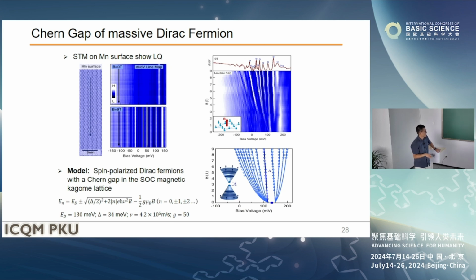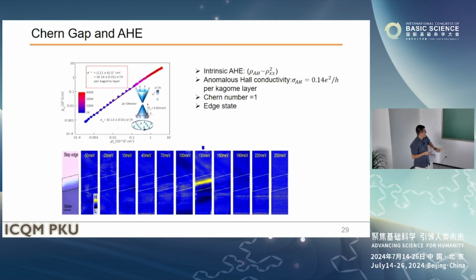Okay, so how do we prove this delta is nontrivial, or what is the Chern number of that? That needed our measurement of the anomalous Hall effect. So basically, we observe a purely intrinsic anomalous Hall effect, and the anomalous Hall conductivity, meaning using the anomalous Hall resistance divided by the square of the longitudinal resistance, equals 0.14 quantum per kagome layer. So what we observe is that our Fermi surface is below this gap, and that gives you some significant Berry curvature, but it's less than the quantum number. So this model exactly follows our measurement, indicating the Chern number for this gap equals 1. So that's a good consistency.